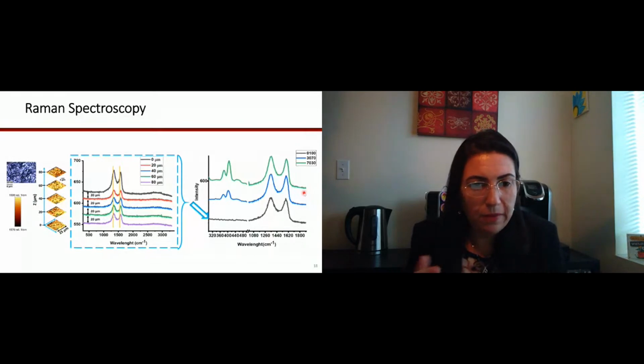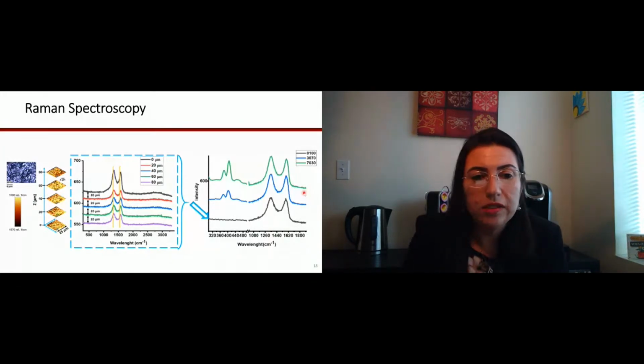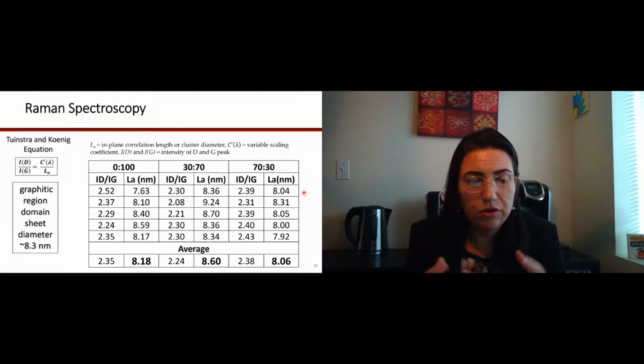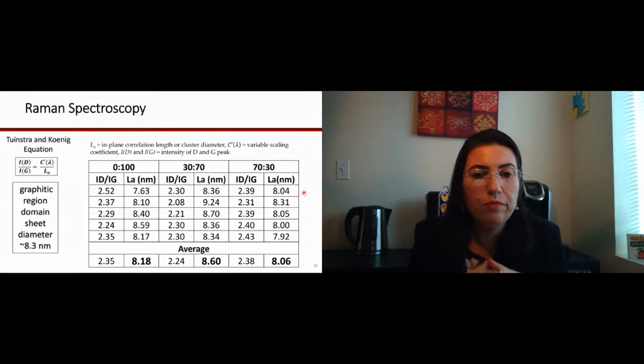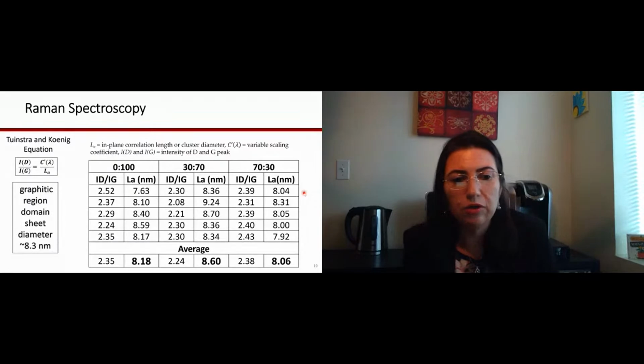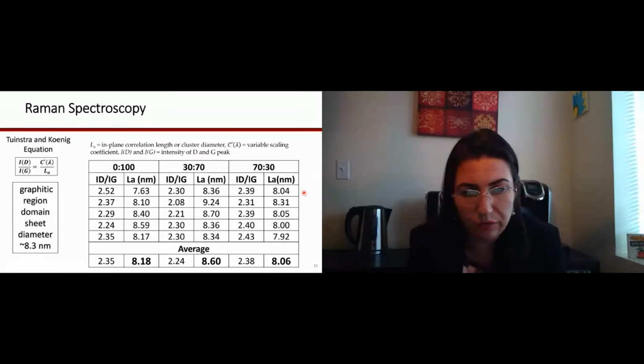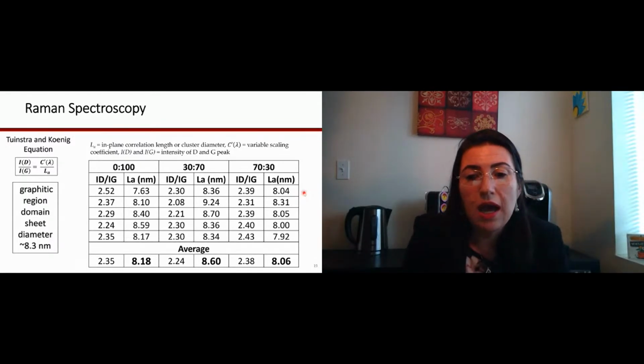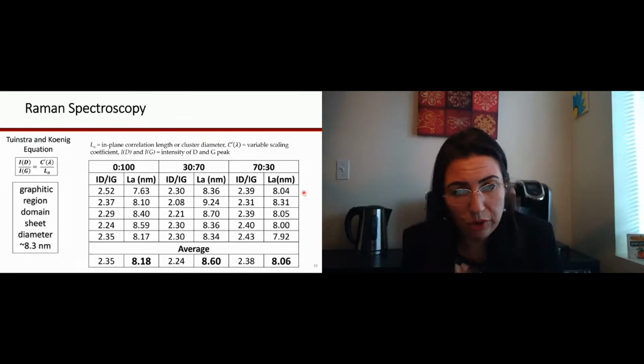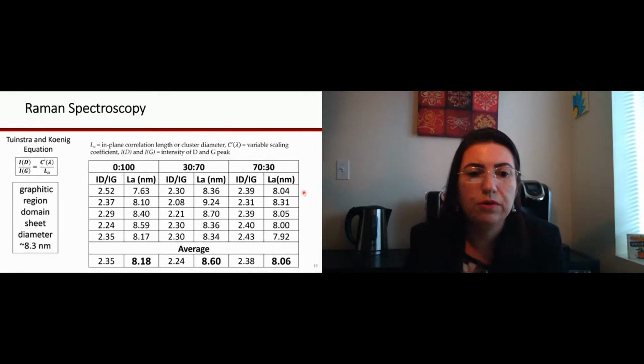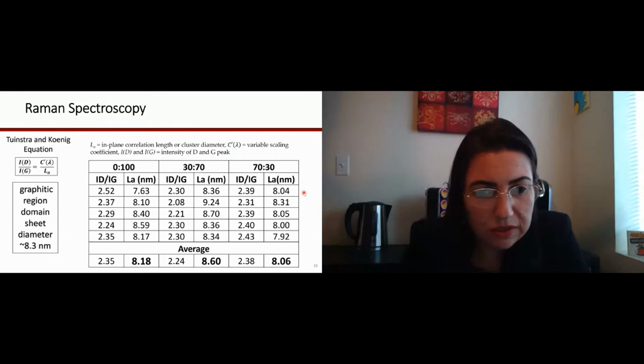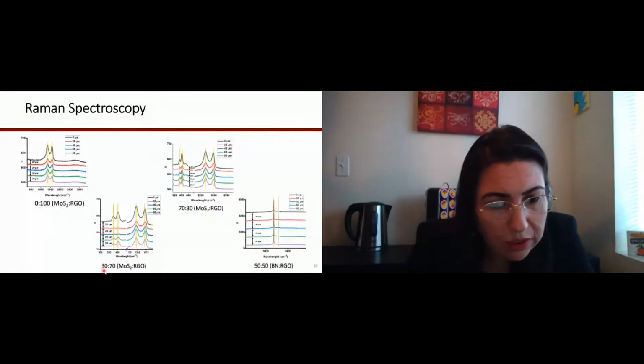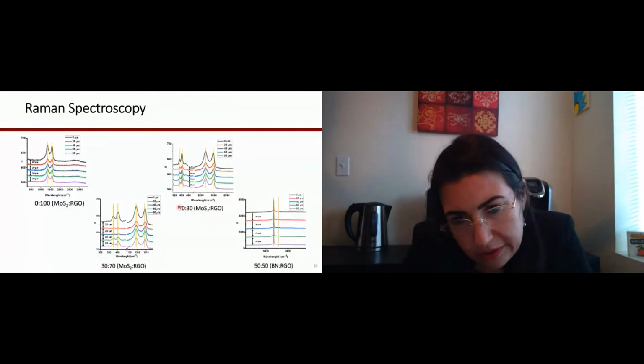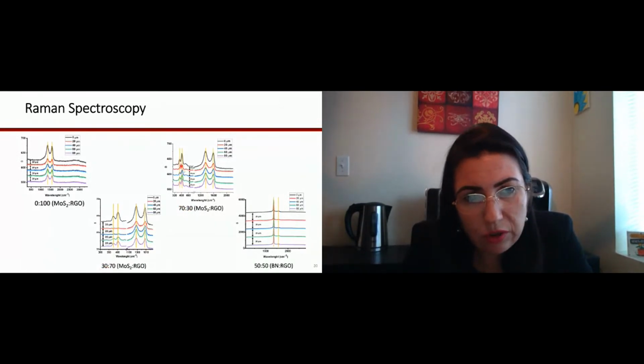Why did we talk about the vibration? Once we want to learn about the electrical characteristics of it, we need to understand how big those graphene sheets are. And using that data, we can obtain the average size of the graphitic region domain. So that is about 8.3 average that we got from our samples. And another thing that was even more important in this case, looking at all different samples. As you can see here, we don't see the MoS2 in this case because we have little MoS2. As we increase the amount of MoS2, you see the peaks throughout the whole device.